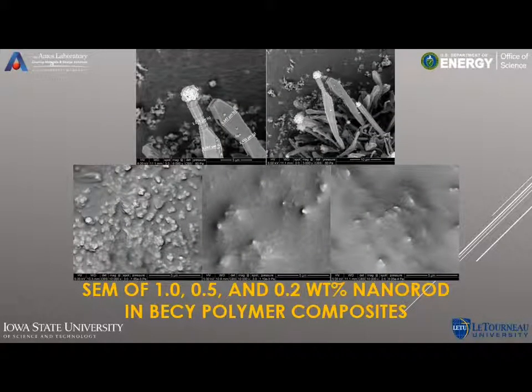These images are also scanning electron microscopy images, as you saw before for the first research segment. And they're looking at the surfaces of the polymer here at the bottom, and then at the nanorods up on top. These nanorods, as I mentioned, were formed by microwaving nanotubes. And that was something that we sort of discovered accidentally in the process of reducing the metal oxides in the presence of nanotubes in the microwave oven.